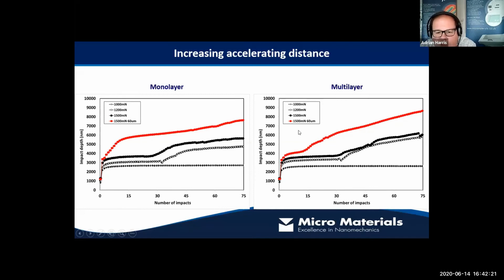So what we've done then is we have used a bigger acceleration distance. We've extended out to 60 microns acceleration distance. That increases the velocity and therefore the energy that we're sticking into the impact. And now what we find is that this monolayer coating fails much quicker than the multi-layer.